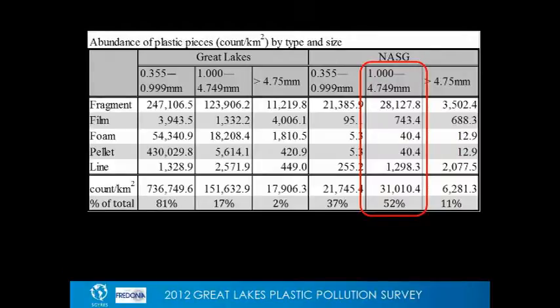And this is really true of most oceanic plastic debris. Most often they're in that 1 to 5 millimeter category. I want to contrast that to what we found in the Great Lakes. So 80% of what we found in the Great Lakes was actually smaller than that.